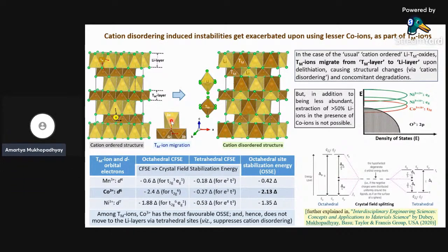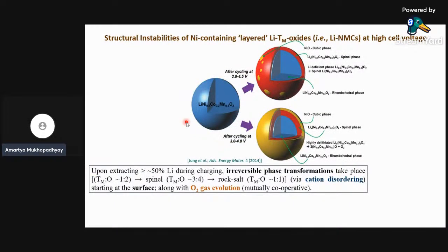So now, one has to suppress the transition metal migration from the transition metal layer to the lithium layer, and that is what we tried to do in one of our studies, as I will show here. Before that, with this transition metal migration and cation disordering, the structure slowly changes from a nice layered structure to a spinel structure and then a rock salt structure, starting from the surface. And these rock salt and spinel structures have very minimal lithium ion transport; they render lithium transport highly difficult compared to the nice layered structure.